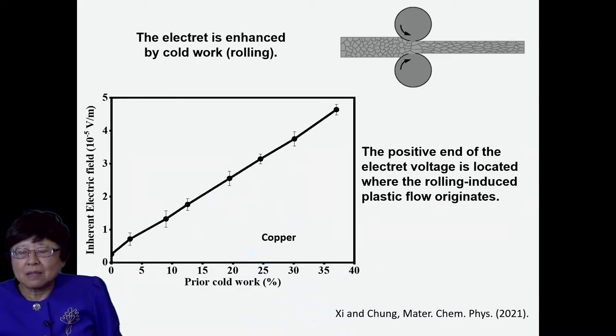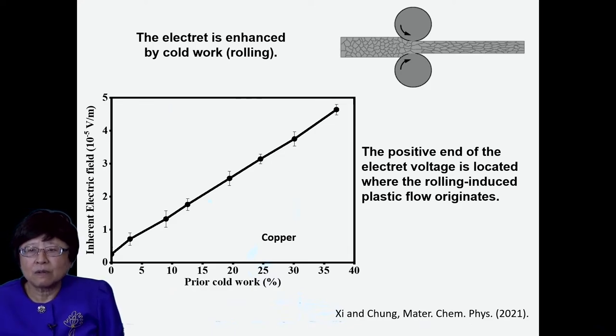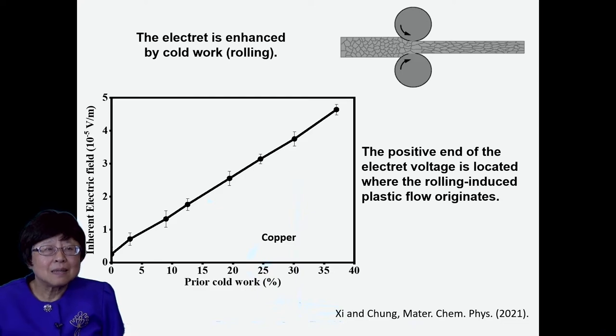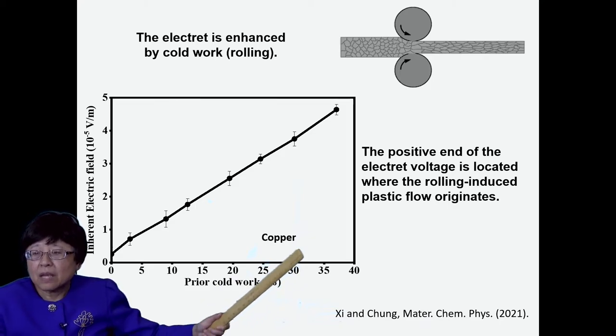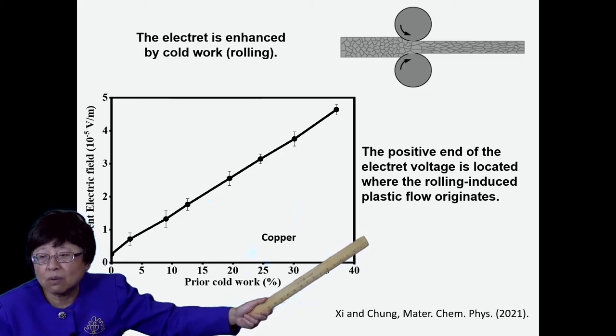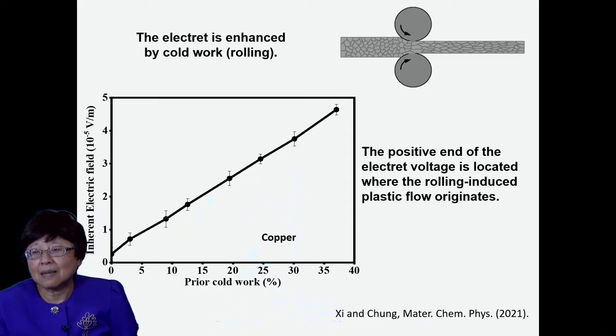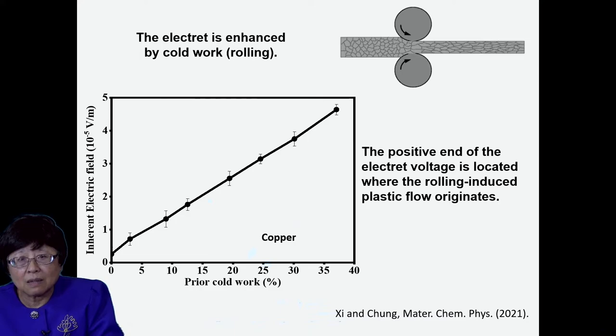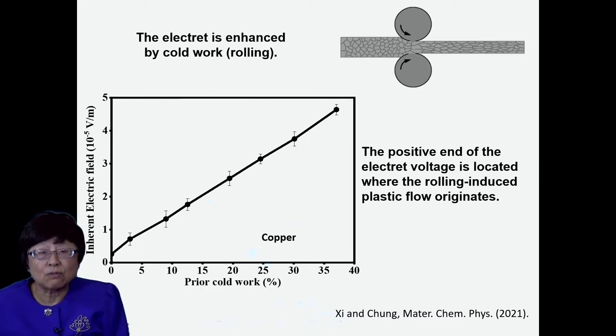So we can subject a metal to cold rolling and look at the effect of the cold work on that inherent electric field. And we see that the voltage increases with amount of prior cold work. The cold work affects the microstructure. And the microstructure, in turn, affects the abundance of atom sites where the electron-atom interaction occurs. The more abundant those sites are, the greater the extent of electron-atom interaction, and the bigger the electret's voltage or electric field. Moreover, the positive end of the electret voltage is located where the rolling-induced plastic flow originates. This means that the electrons move along with the atoms during the plastic flow. Another indication of electron-atom interaction.